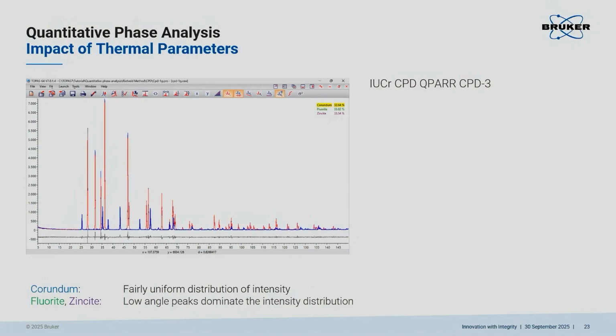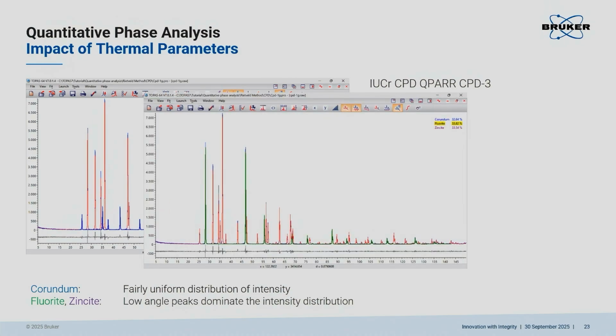So this here is sample number 3 from the quantitative phase analysis round robin. Blue is the corundum. Of course, there's always an intensity drop towards high angles, but it's not a lot actually in corundum. But if you compare that with the fluorite, it becomes obvious what I want to tell you.